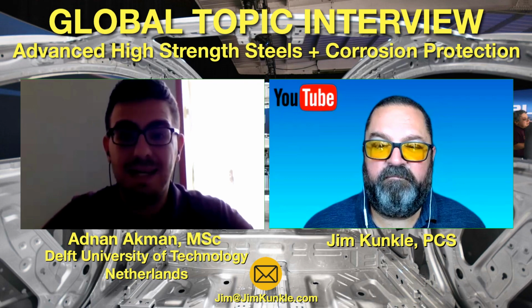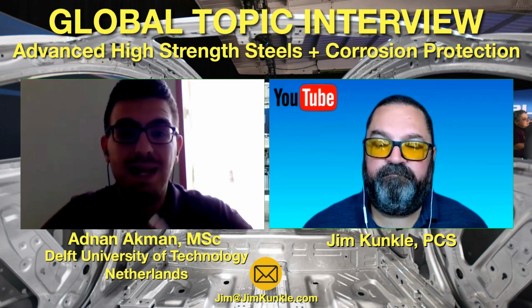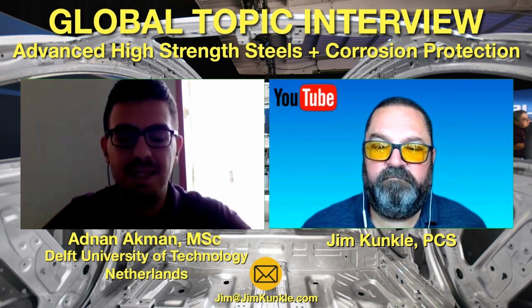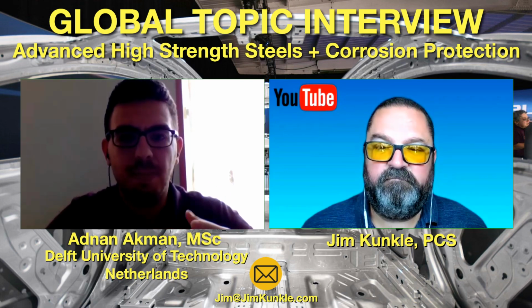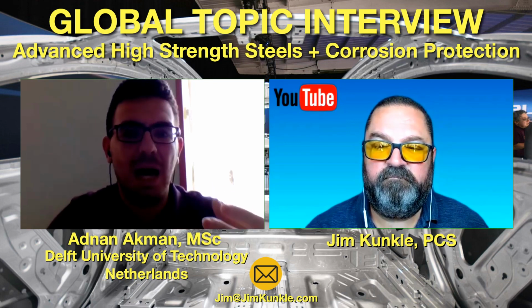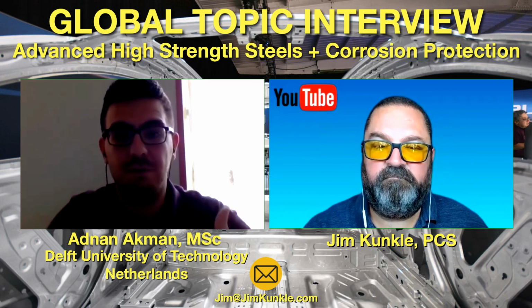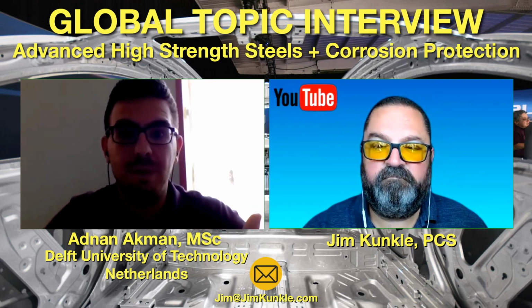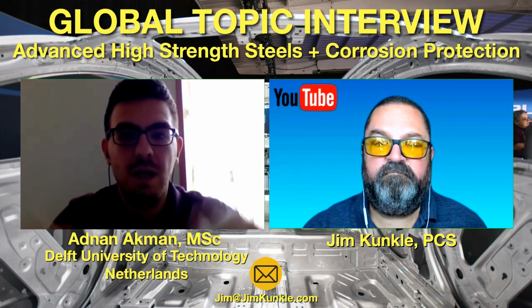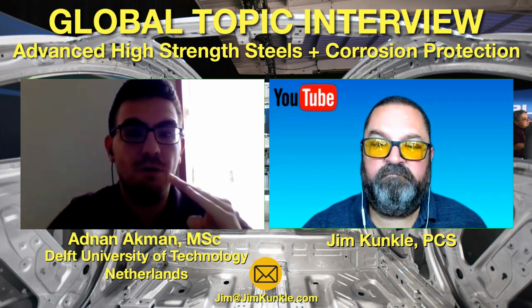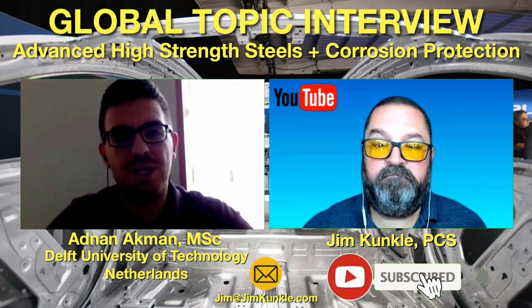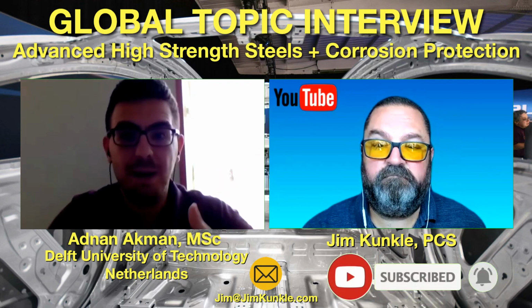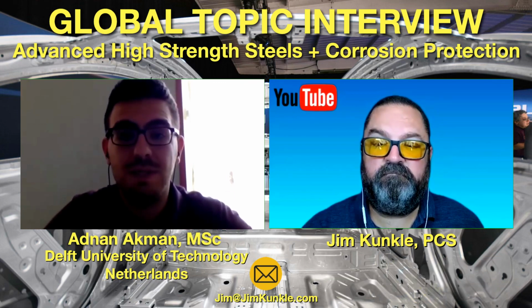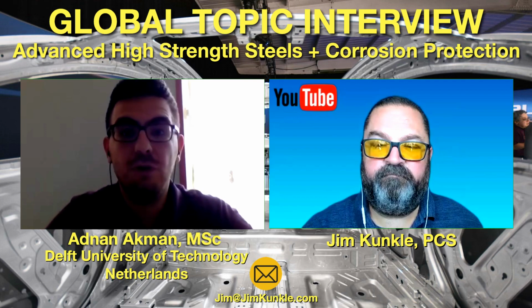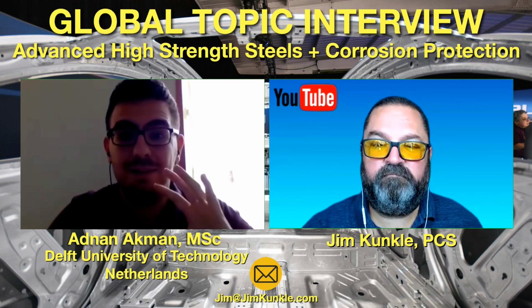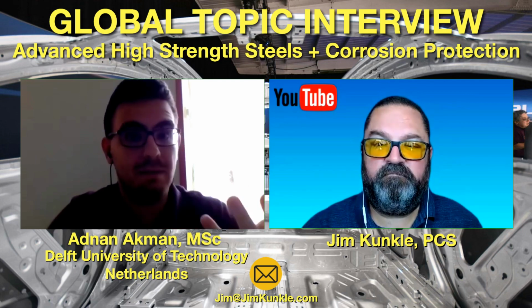What about second generation advanced high strength steel? For example, I mentioned twinning induced plasticity, also called TWIP steels. So twinning is a mechanism where we see deformation twins by the help of a deformation in the microstructure. I mean, we are applying a deformation, kind of deformation. It can be a crash. With this deformation, it is possible to see deformation twins in their microstructure. With these deformation twins, the twin boundaries act as a grain boundary in the steel, and it will increase the strength of the steel. Normally, TWIP steels are fully austenitic steels. I mentioned that these advanced high strength steels are mostly complex steels, but this is fully austenitic steel.